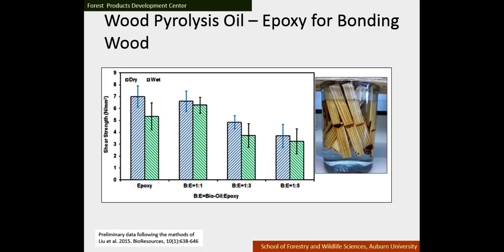I guess we all think that what we do is novel. I think this is really novel from a practical perspective, but I keep submitting this to NSF and it keeps getting rejected, so maybe it's not as great as I think it is. But I think this is novel because I told you earlier that when you test epoxy, you glue two pieces of wood together with epoxy and you throw it in water, it falls apart. So you can see that here, you can see the strength reduced. But if we mix enough bio oil in there, and you have to put enough bio oil into the epoxy